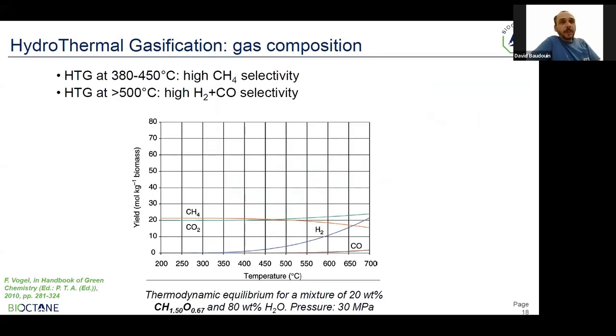So here I show you the typical concentration or yield of gases at a set pressure, as indicated at the bottom, as a function of temperature. And you can see that methane and CO2 dominate below 450 degrees C, and hydrogen and CO start to increase significantly when the temperature goes up above 500, 600 degrees C. So these, of course, are for a set concentration of a hypothetical composition of feedstock. These can vary, but the trend is at high temperature, hydrogen is favored, while at lower temperature, methane is favored.